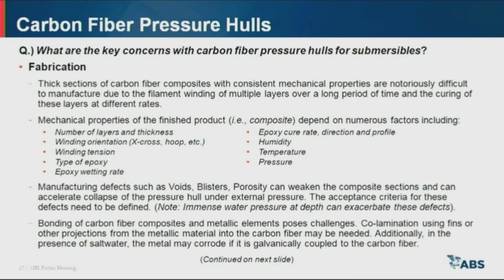So one of the processes used for fabricating carbon fiber composite pressure hulls is the filament winding process, in which the pressure hull is created by impregnating or coating the carbon fiber strands with epoxy and then winding them in a precise geometric fashion over a mandrel. So a mandrel is basically a tool in the shape of a cylinder. So on the cylinder, you wind the carbon fibers which are impregnated with epoxy. And then you cure that cylinder in an oven at 1 atmosphere or in an autoclave under pressure.